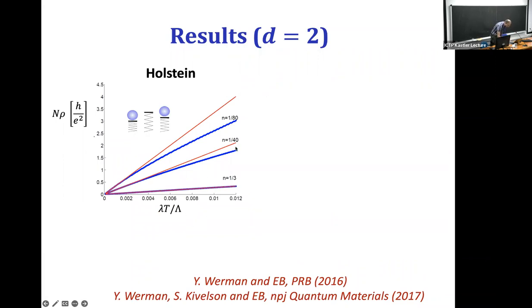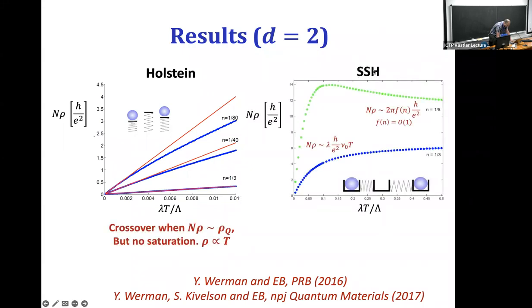So there is a crossover, but there isn't the so-called resistivity saturation, which occurs in many real metals when k_F l approaches one. On the other hand, in the SSH type variant of the model, it starts linearly as well. That's the usual Bloch-Grüneisen behavior. But then when k_F l becomes of order one, times some function of the density, there is a resistivity saturation to a value of the order of h over e squared. This is a 2D model. So this is the so-called resistivity saturation. It's a possible explanation of that behavior, which is actually seen in many metals.